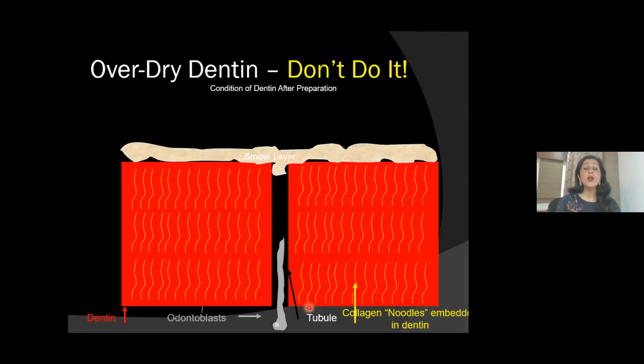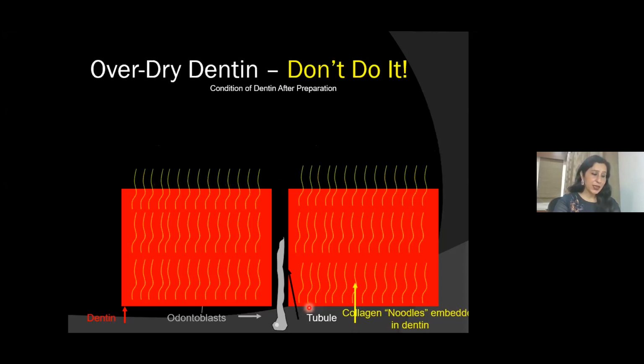So when we are talking about total etch technique, what do you do? What is the right way of doing it? Because if you are using this, then knowing the right way would be a help. When you apply etchant and rinse it after 15 seconds, I told you that the etching time is 15 seconds. There is moisture in the collagen strands of dentine, which float like noodles. Now, if you blow air vigorously on dentine and enamel to see the frosty appearance, because we've been taught like this, to blow hard air to see the frosty appearance of the enamel and dentine so that you know that you have etched well, that is wrong.